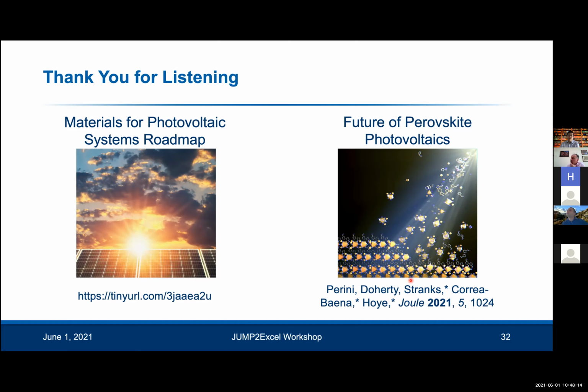Yeah, I mean that actually is so. Okay, so what you're talking about is the anti-reflection coating. That is currently used in commercial silicon solar cells. You would, for example, use silicon nitride for anti-reflection coatings. For new technologies, you have to think about what the stacks are, because the most effective anti-reflection coating depends on the refractive index of the various different layers that you're using. And of course, if you change material, you change the refractive index.